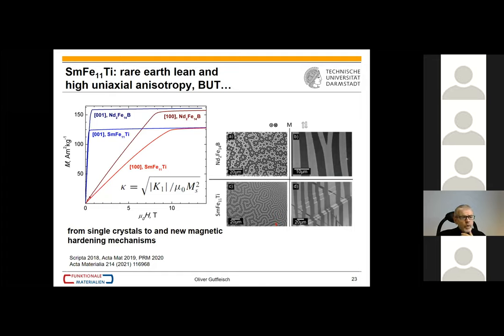Okay, so I have one more example here. This is now a so-called rare earth lean system because we only have one samarium and 12 iron, or better, a little bit of titanium to stabilize this 112 structure. So we made single crystals. Here's our classical 214-1. And we also made the 112 single crystal. And if you use the coercivity, the magnetic hardness factor as defined here, then you actually can see that the coercivity for 112 is higher than that of 214-1.